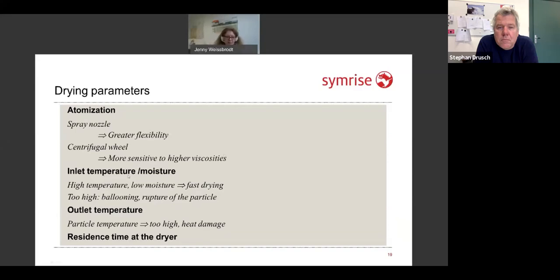The inlet air temperature and the moisture. If you have a very high inlet air temperature and a low moisture, you have possibly a very fast drying. But if your temperature is too high, you have a drying on the surface of the droplet, it tightens up, it gets very dense, the water can't come out, and this leads to a rupture of the particles. The outlet air temperature, as mentioned, is the temperature the particle itself will get. If it's too high, you can have a heat damage if you have very heat sensitive materials.